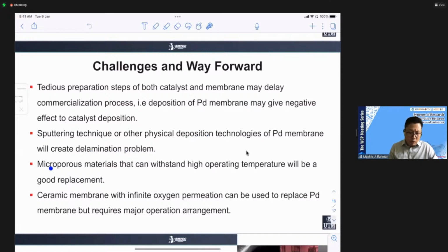So we try to work on microporous material. Actually, that can withstand high operating temperature, because there are a lot of microporous materials such as zeolite and MOF that can be used to extract the hydrogen. But there is another way, not to use palladium membrane for hydrogen separation. We can use the ceramic membrane, for example, perovskite membrane. Perovskite membrane is known to have infinite oxygen permeation, so we need to change the operation arrangement so that the perovskite can help to produce hydrogen for fuel cell requirement.